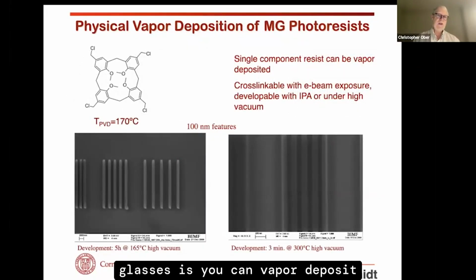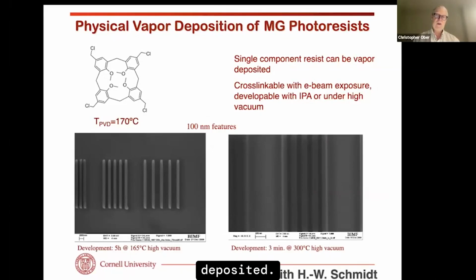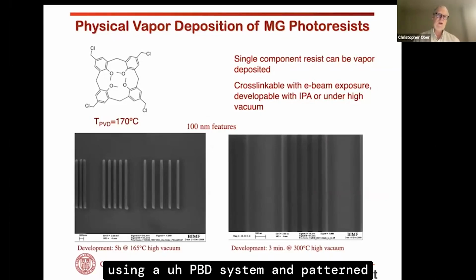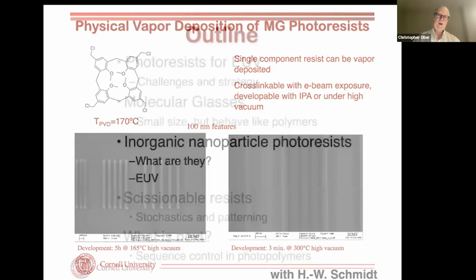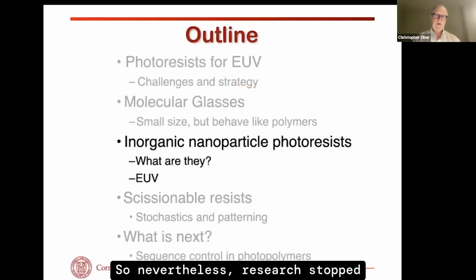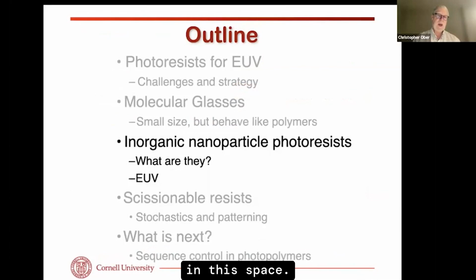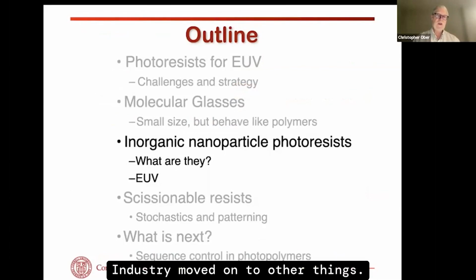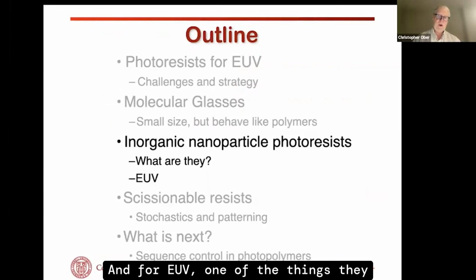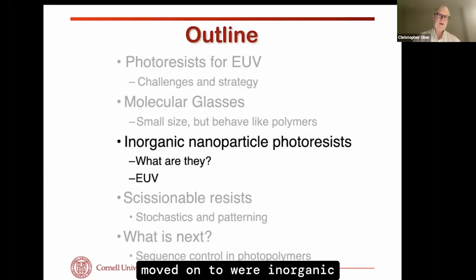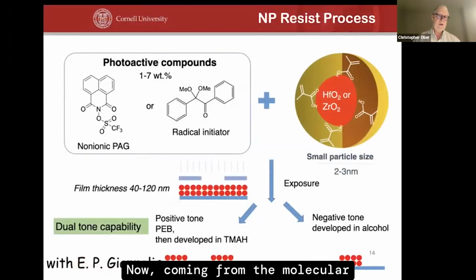Another advantage of molecular glasses is you can vapor deposit them. And so this is an example of a molecular glass molecule that was deposited using a PVD system and patterned using E-beam. So nevertheless, research stopped in this space. Industry moved on to other things. And for EUV, one of the things they moved on to were inorganic nanoparticle photoresists. Now, coming from the molecular glass size, to me, these are basically inorganic molecular glasses.